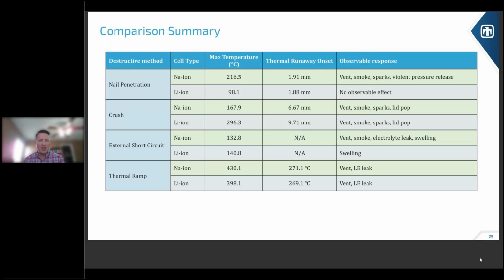Both cells responded with a similar observable response. And then we did an external short circuit. They both got about the same temperature, but as I mentioned, the sodium ion cell actually had the audible vent with flammable gas release and liquid electrolyte coming out of the cell. And the last test that I'm summarizing here, at least the one that we compared to lithium ion, is thermal ramp. And interestingly, we got a very similar response between both lithium ion and sodium ion. So you can go ahead and start tabbing through those slide transitions.